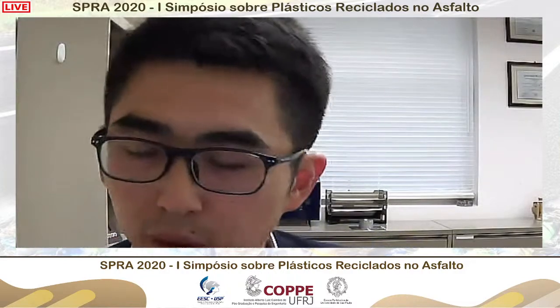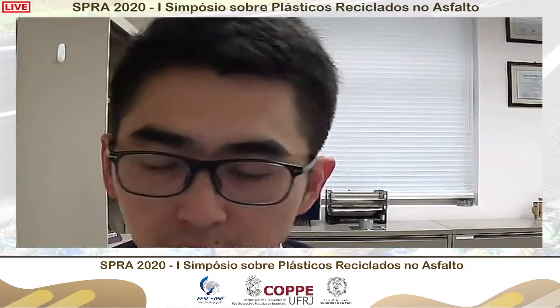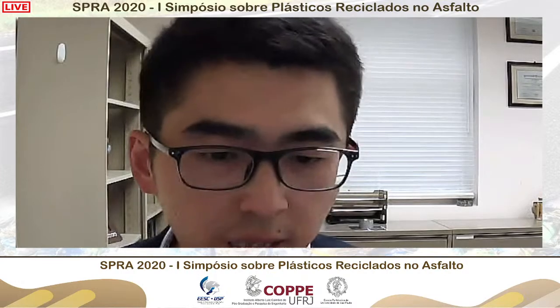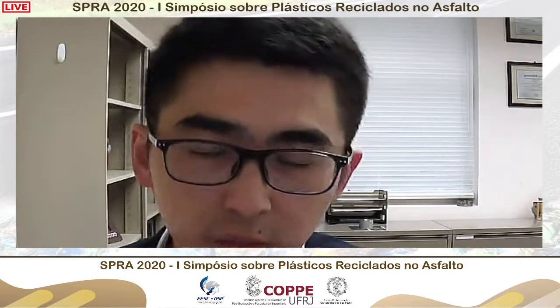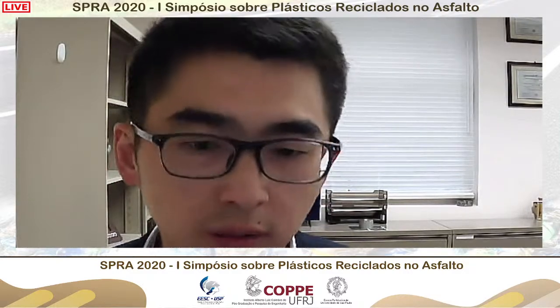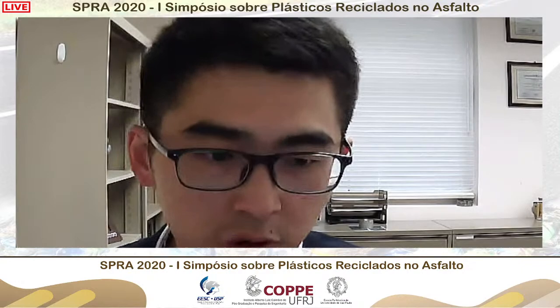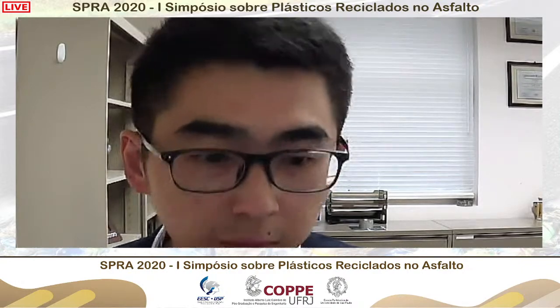Yeah, I agree. That's a good point. That's why the state agencies here in the US prefer the wet process over the dry process, because on the wet process, they can better control the homogeneity or the quality of the mix. But when we do the dry process, we don't have 100% control on the distribution or the homogeneity. So if we have plastic not uniformly distributed, and the way we run the lab test, either ideal CT or cyclic fatigue, there might be some localized agglomeration of the plastic that can give different results depending on where we're testing and where the failure started.